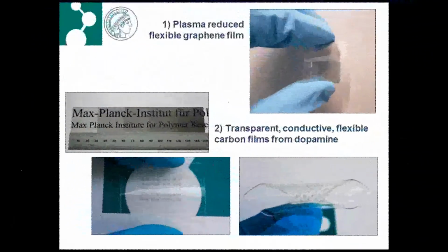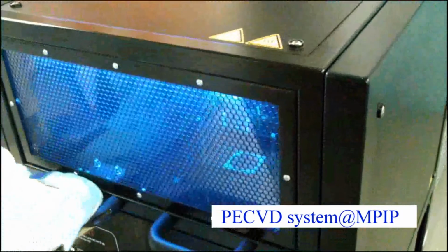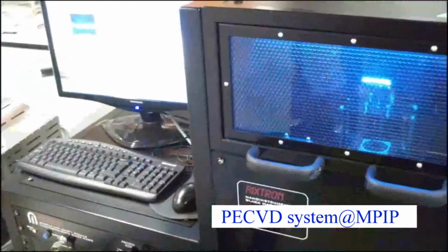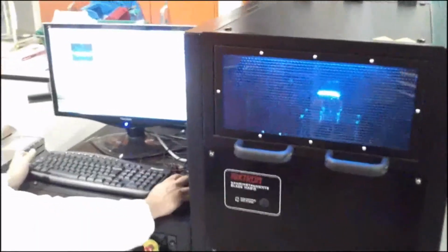Graphene oxide films were treated in CH4 plasma condition. The treatment time can be as short as 10 seconds, yet resulting in samples with a sheet resistance of 5.2 kilo-ohm per square and about 80% transmittance.